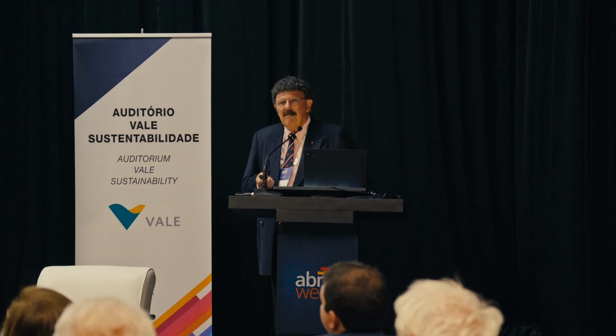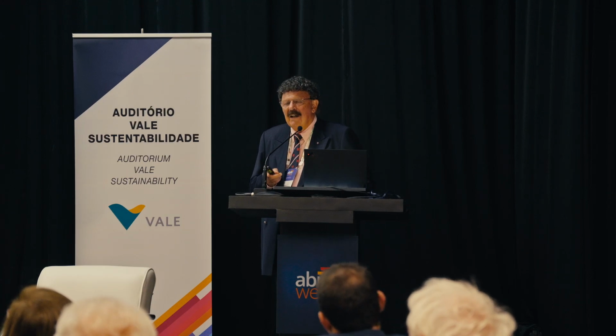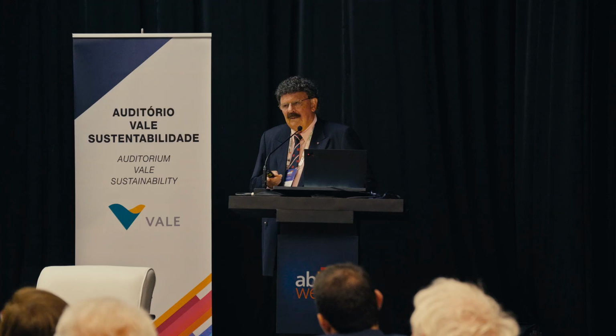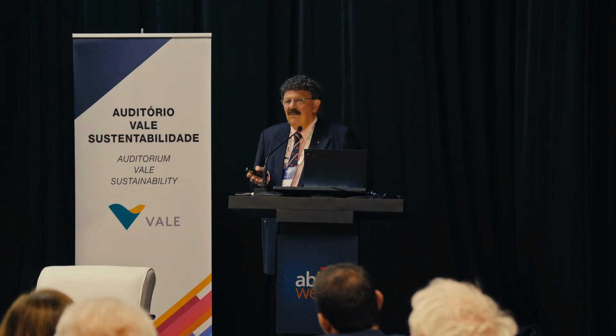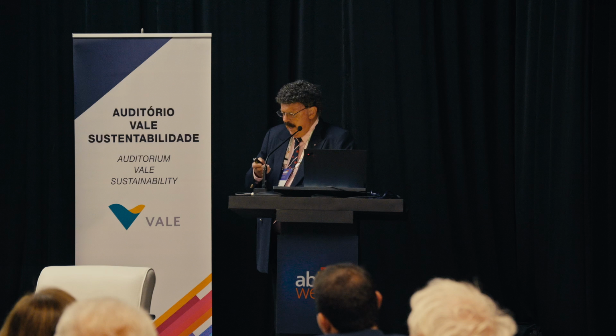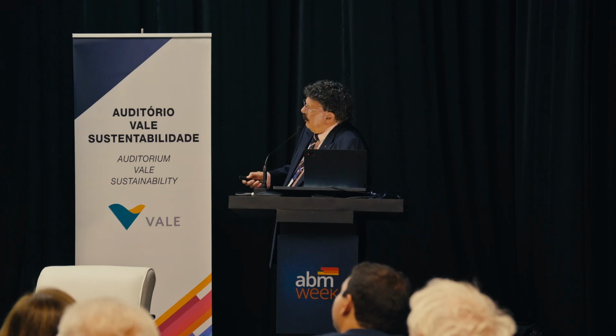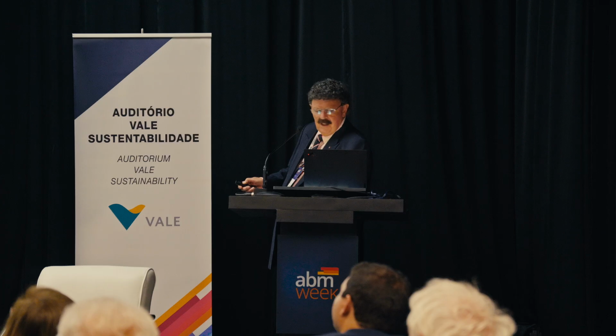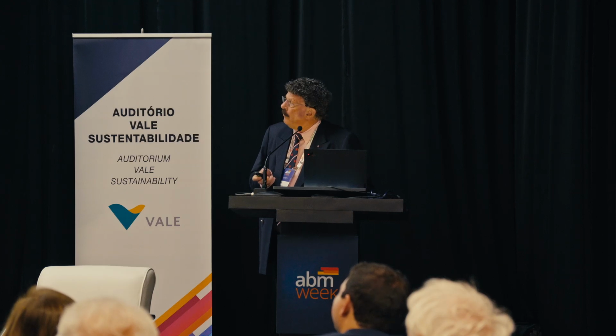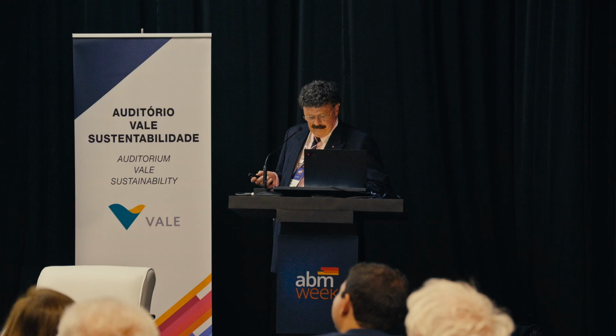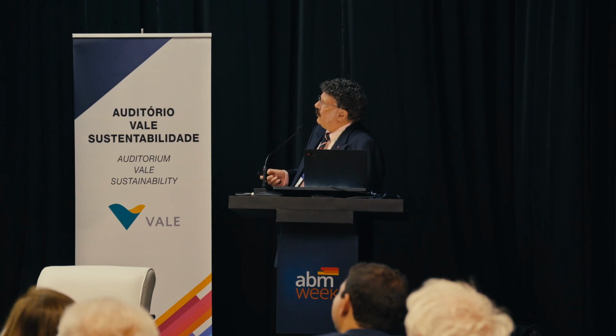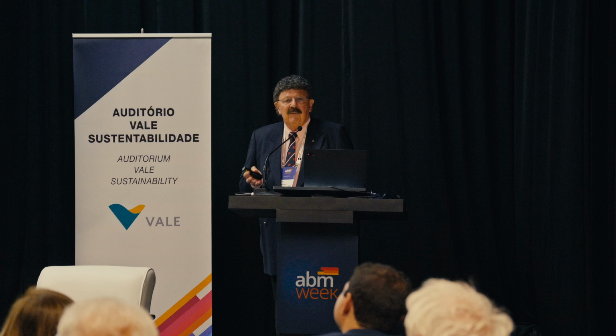Most of the properties that have been measured on these refractory high-entropy alloys are measured in compression. And compression is not a good source for many of the fracture properties. This is this superalloy in compression. Beautiful, fantastic ductility. Look at the strength here, up around 3 gigapascals, high ductility. But if you measure them in tension, you get a very, very different story. This is the data in tension. The strength drops from 3 gigapascals to 0.2 gigapascals, and the ductilities are all very, very small because they're brittle materials, and this is classic.